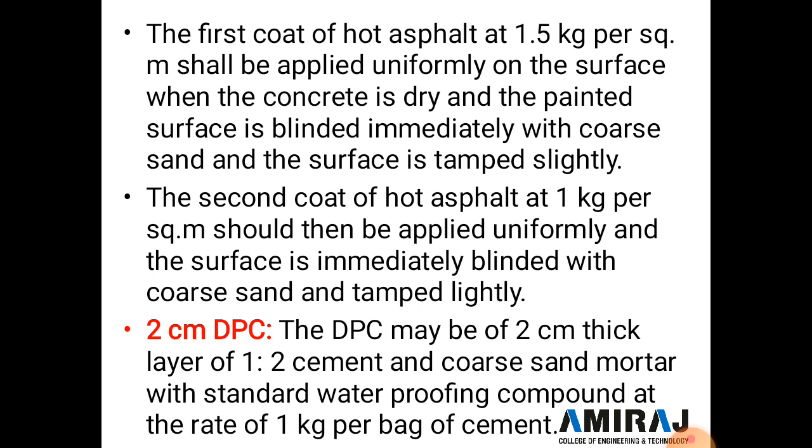Now next is a 2 centimeter DPC. So the DPC may be a 2 centimeter thick layer of 1:2 cement and coarse sand mortar with waterproofing compound at the rate of 1 kg per bag of cement.